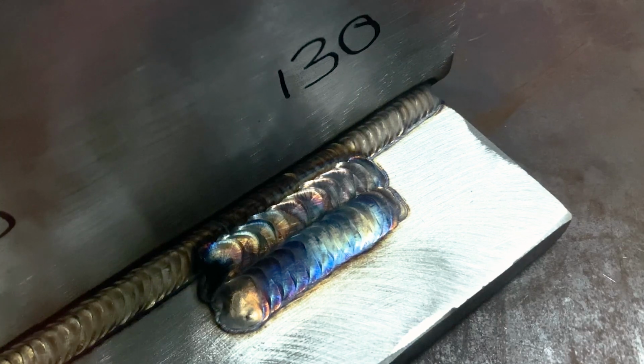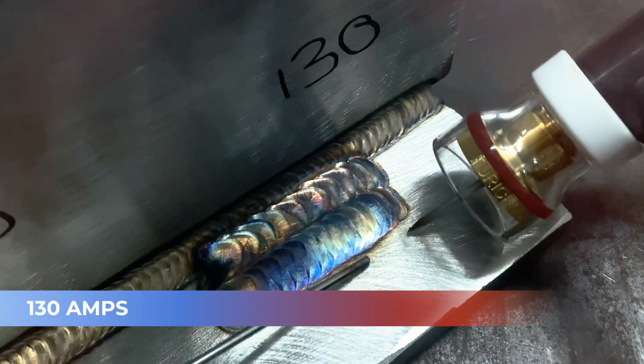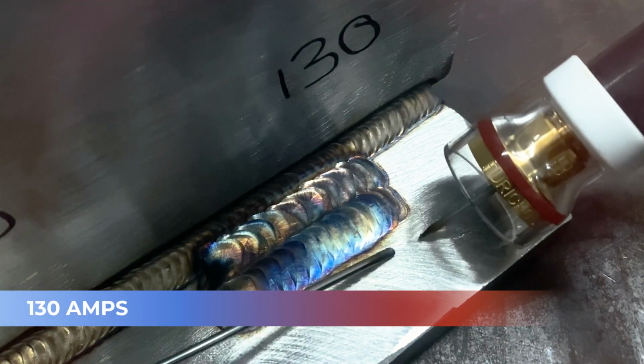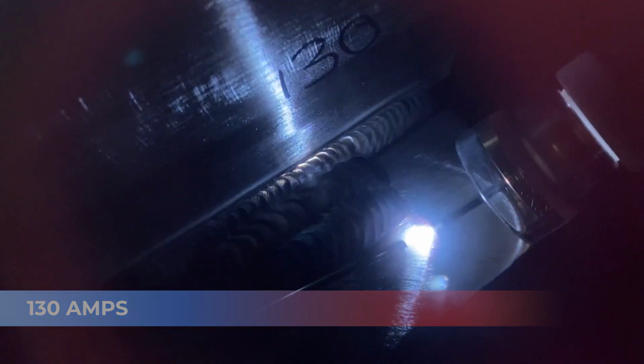And now here, finally, we're going to step it down to 130. Definitely the cooler end of the spectrum as far as this material is considered. And you'll see it's after going from high to low, right? You'll see I'm having to move much slower. I'm really having to wait, let it pause on the sides, let it consume in the middle. That's because I'm probably too cold for this application. In a pinch, it'll work, but it's not ideal. These are the differences and the details that you need to be focusing on.